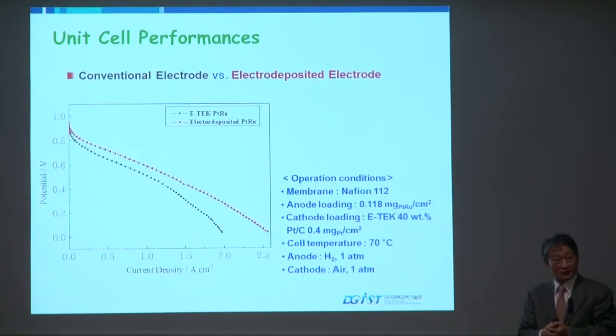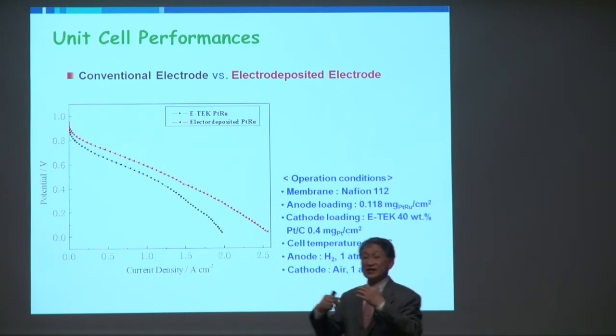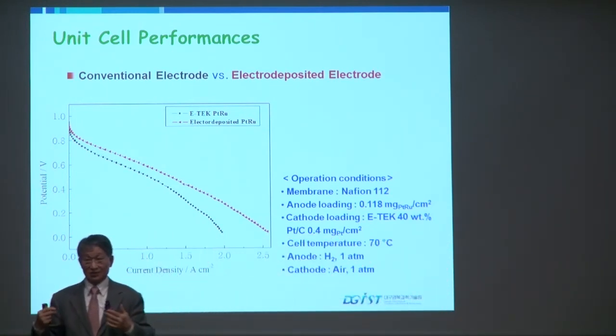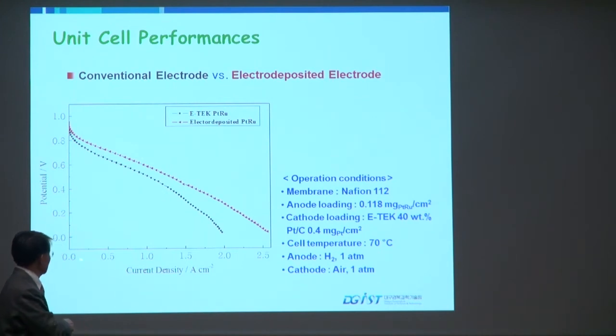Then unicell performance. We utilize this for fuel cell applications. The polarization curve measures the current density with the potentials. The black one is ETEC with the same amount of platinum-ruthenium. We have the same amount of platinum-ruthenium in the ETEC catalyst as well as the electrochemically deposited ones. We carefully calculate this and make these two different MEAs and compare these two MEAs for fuel cell applications.